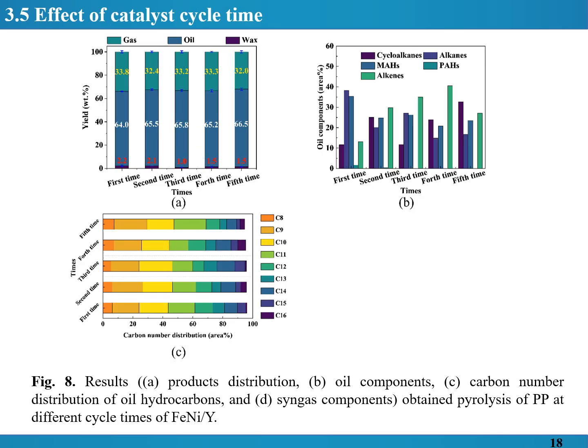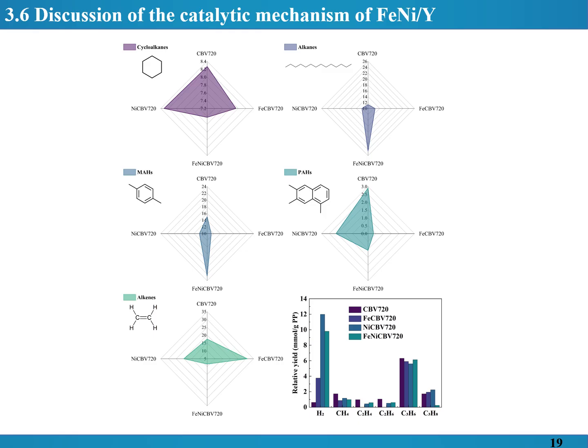Figure 8 shows the results obtained from pyrolysis of PP at different cycle times of iron-nickel supported by Y zeolite. The regenerated catalyst results in an increase in olefin content, while monoaromatic hydrocarbon content decreased. The distribution range of carbon 8 to carbon 16 hydrocarbons in the liquid oil showed little variation, indicating that the number of cycles of different catalysts has had little effect on the carbon number distribution of carbon 8 to carbon 16 hydrocarbons. Overall, iron-nickel catalyst pyrolysis supported by Y zeolite has potential for converting waste plastics into oil. This figure shows a comparison of oil, chemicals and gas product rates by using different catalytic metals.